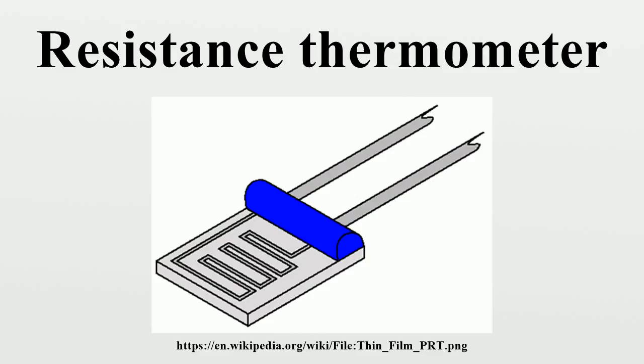Disadvantages of this type are that they are not as stable as their wire wound or coiled counterparts. They also can only be used over a limited temperature range due to the different expansion rates of the substrate and resistive deposit, giving the strain gauge effect that can be seen in the resistive temperature coefficient. These elements work with temperatures to 300 degrees Celsius without further packaging but can operate up to 600 degrees Celsius when suitably encapsulated in glass or ceramic. Nowadays there are special high-temperature RTD elements which can be used up to 900 degrees Celsius with the right encapsulation.